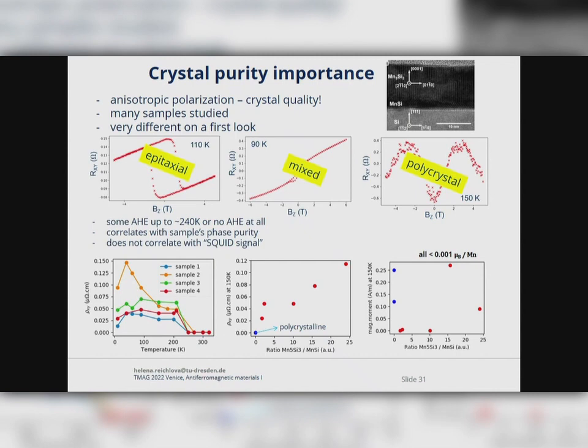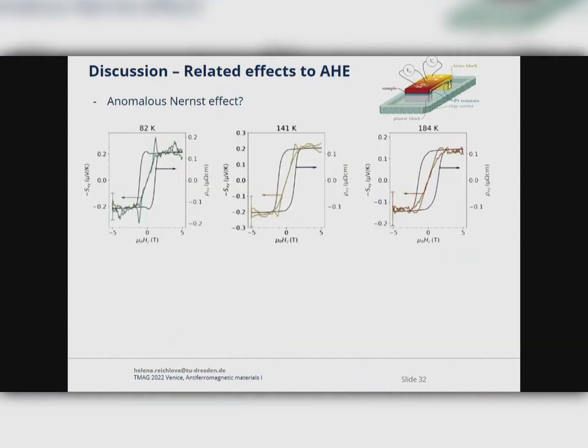So I mentioned that this anomalous Hall effect has related effects such as the anomalous Nernst effect. And this is something which, of course, interests us a lot. We already prepared samples where we applied a thermal gradient instead of electrical current, and we measured the transversal voltage. And indeed, we see a signal, with saturation at similar fields. The colored data are the anomalous Nernst data, and they are overlaid with the anomalous Hall data measured simultaneously.